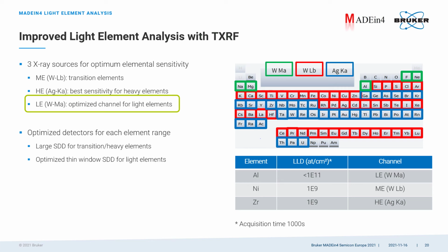In the table below, you see the lower limit of detection for the reference elements. The detection limit for aluminum used to be around low E12 atoms per square centimeter, which is now improved to 1E11 atoms per square centimeter and lower, so more than a factor of 10.